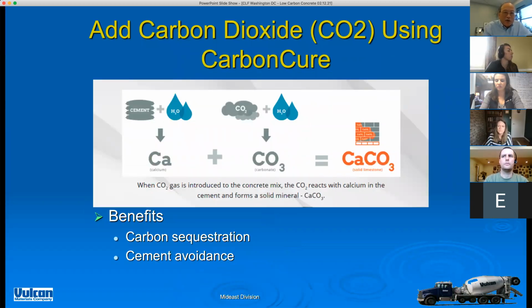All right, I'm not going to go into this much. We're talking about adding CO2 to concrete. That's the chemical reaction that takes place, and basically we're generating calcium carbonate, or really limestone, in the process. One of the advantages that Eric didn't mention is that the limestone that is generated is very different from the limestone that cement companies add to the cement when they're grinding their clinker. The limestone that is generated using the CarbonCure process is nanoparticle size, very, very small.